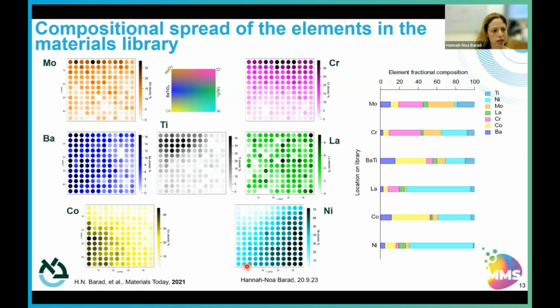These are composition heat maps of the different elements composing the materials library that we formed. So you can see nickel has a very nice gradient from 70% to almost zero, cobalt the same, etc. Some materials we had some issues with depositing, but these are known things because the materials degrade over time. However, we still decided to use them.